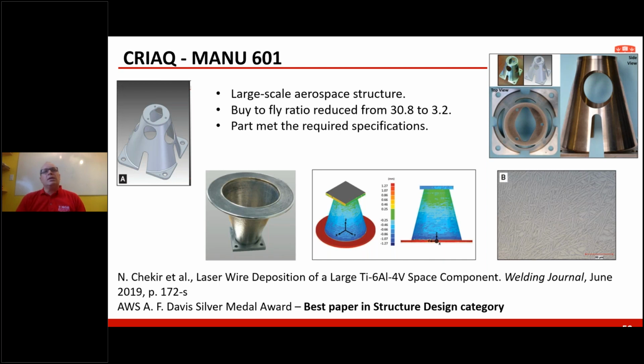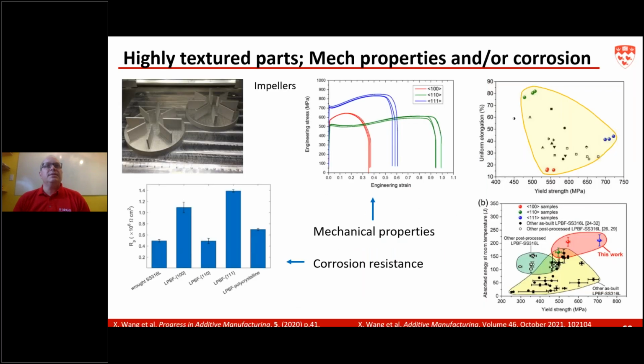At the beginning, when this part was fabricated, it had a buy-to-fly ratio of about 31. And now with the 3D printing, within 2.5 days, we managed to bring this part to a buy-to-fly ratio of 3.2. So you can see the sequence here that went through, where we fabricated the bulk of the part. Then we looked at its geometry, dimensional, and tolerance. Then we characterized microstructure and mechanical property to end up with the final component.